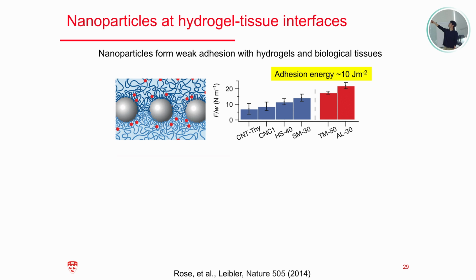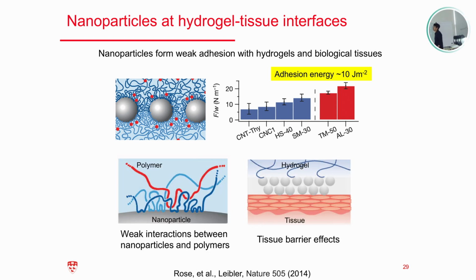You see, again a very familiar number, on the order of 10 joules per meter squared. They screened different kinds of polymers and different kinds of nanoparticles, like carbon nanotubes or silica-based nanoparticles. And those low adhesion energies come with reasons. The reason is that the nanoparticle only forms a weak interaction with the polymers inside the tissue or in the hydrogels, and also, because of the larger size of the nanoparticle, it's very difficult for them to penetrate condensed tissue barriers such as the epidermis of the skin.